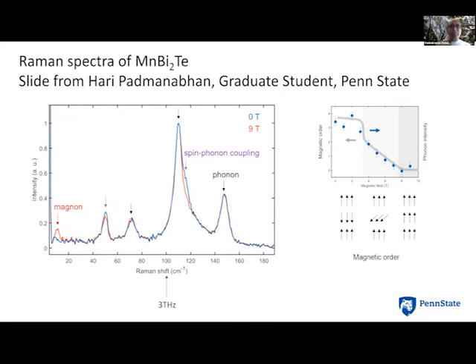If you pick up on that, on the top right, you can see the gray line is the magnetic order that's evolving as a function of magnetic field. And the blue dots are this change in the shoulder around where the spin phonon coupling is written. You can see it follows very well. So it's not just lattice vibrations. You can also learn something about magnetism by Raman spectroscopy.